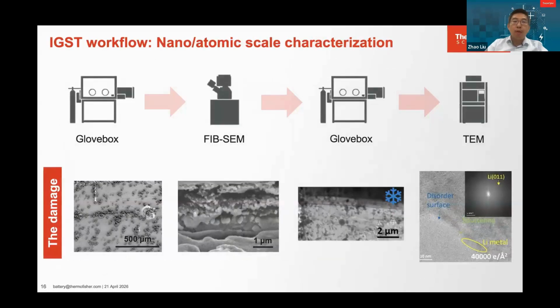Next I will show you the most complicated but the most critical workflow, which is the nano and atomic scale characterization. As you can see, the sample goes through a journey from the glove box all the way to the TEM, and it has multiple transfer steps. When you transfer from the glove box to the FIB-SEM, the sample has a risk of exposure to the environment, causing damage. Inside the FIB-SEM, the ion beam and material interaction can cause sample damage as well. And then when you transfer the lamella from the glove box to the TEM, different transfer methods could also cause contamination on the surface. As you can see here, ice crystals grow on the lamella.